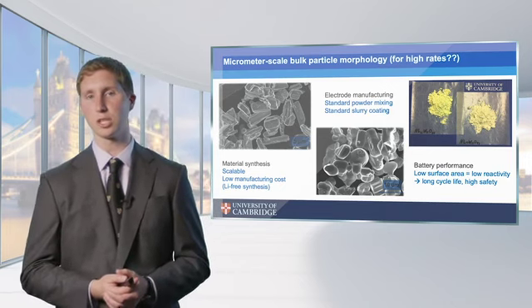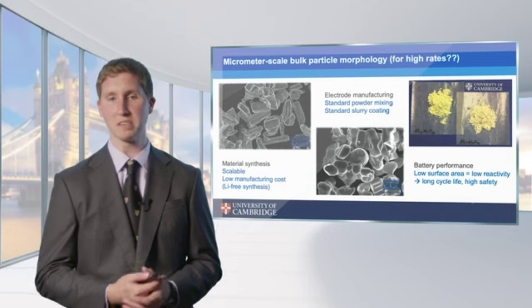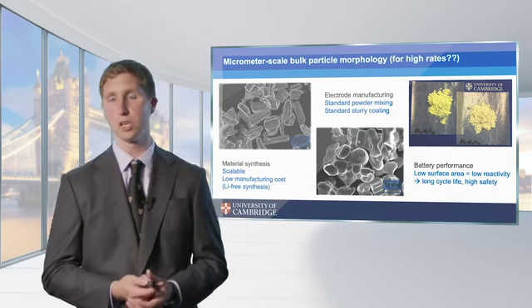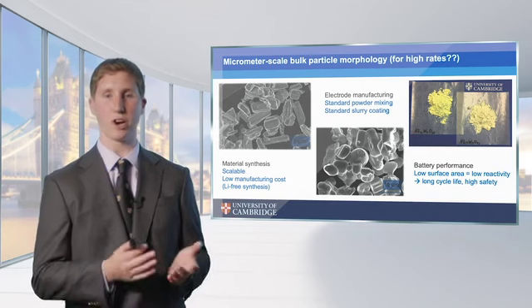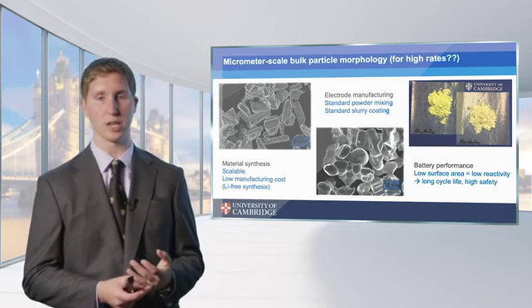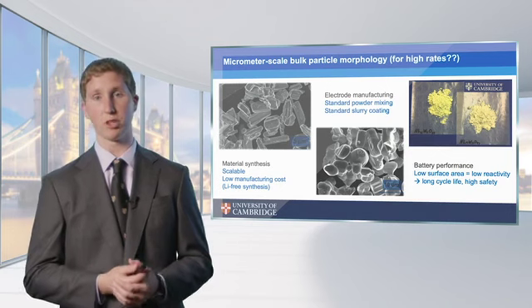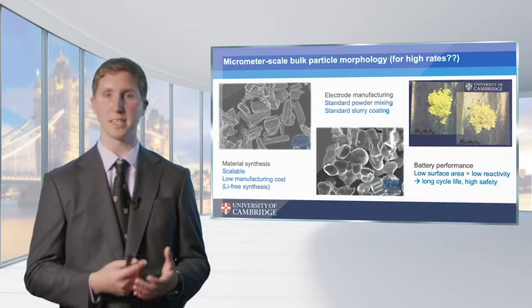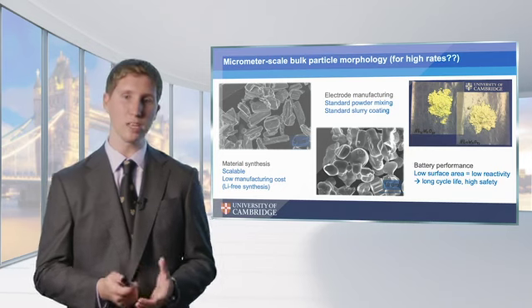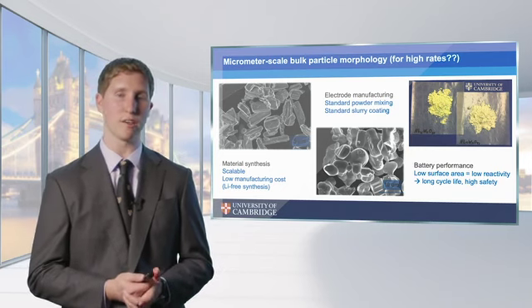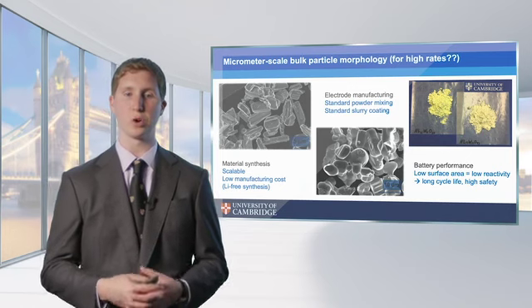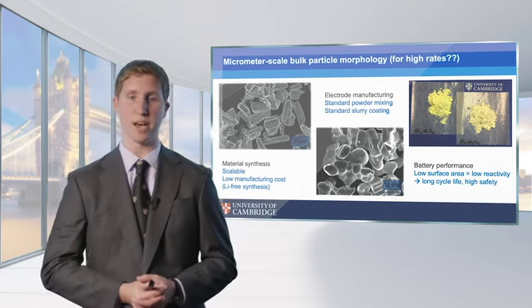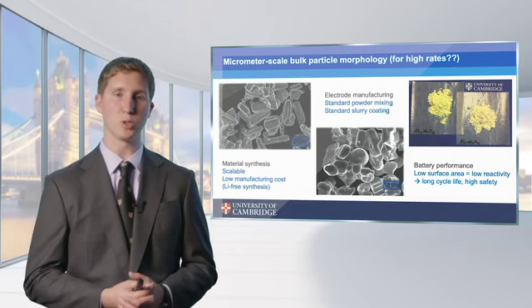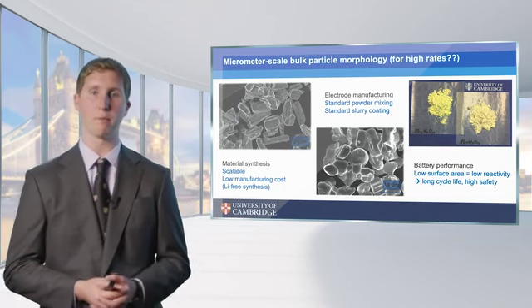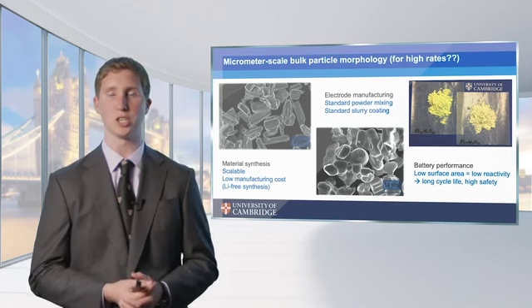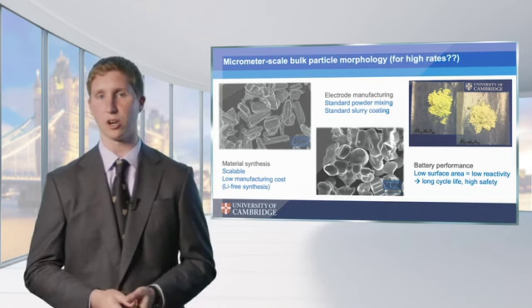And then finally, once we actually get to a fully formed battery, there are significant advantages to having micron scale particles because we'll have a much lower surface area of our active electrode material in contact with our electrolyte. And so that means that we should have low reactivity, minimal gassing and SEI formation, and these will lead directly to things like long cycle life and high safety. And we're enabled to do this only if we have a very fast diffusion such that we can get through, say, 5 or 10 microns of material in a matter of a couple minutes to do full lithiation and delithiation of these particles and access our maximum capacity.